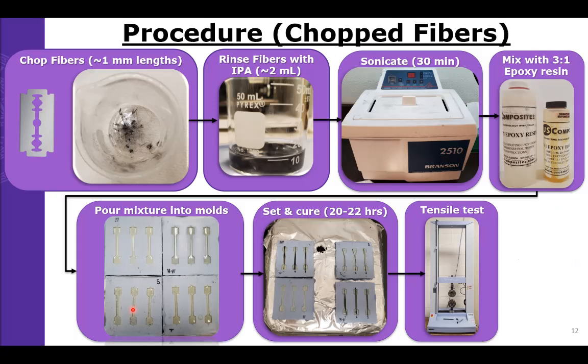Here's the procedure for the chopped fibers. We can see that we chop these fibers to 1 millimeter lengths before rinsing them with 2 milliliters of isopropanol before sonicating in a box sonicator for 30 minutes. We then mix this in with our 3-to-1 epoxy resin to hardener, and then mix the fibers in with that to get a 0.60 milligram per milliliter concentration, and then pour that mixture into the molds and set and cure these for 20 to 22 hours before tensile testing.